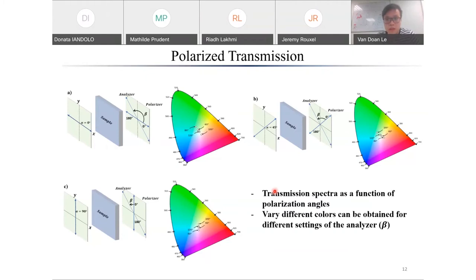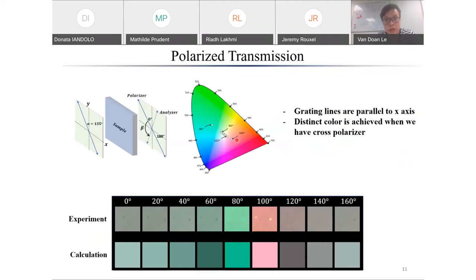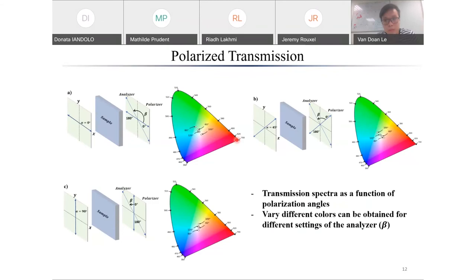This is just a configuration of the different directions of the polarizer and analyzer, with the polarizer at 0 degrees, 45 degrees and 90 degrees. And we can achieve very different colors by simply changing the angle beta. In the case of diagonal polarizer input, you can see it's really similar to the first case, but the 80 degree color here is similar to the 100 degree color here. So all of this is just an indication of the phase variation of the sample.